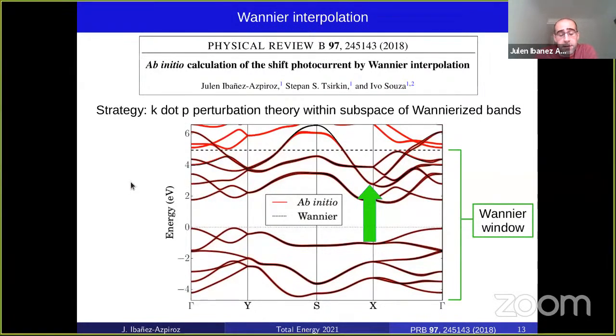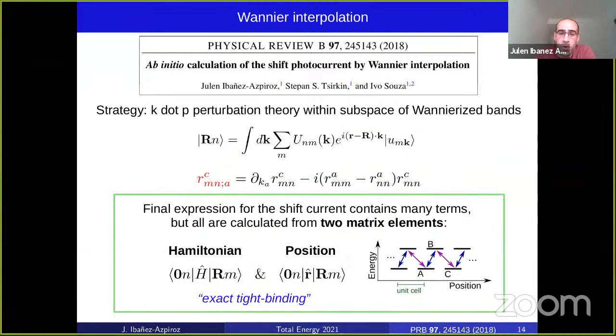Now, broadly speaking, in the Wannier formalism, one needs to consider a finite energy window where one wants to describe properties like the shift current spectrum. So then, if one follows the Wannier procedure, one can end up Wannier interpolating several quantities within this window. And this can be the band structure. This is a well-known example, but not only. One can also interpolate transition matrix elements, and that's our aim. That's where we have worked. We have tried to express the shift current transition matrix elements, and more specifically the generalized derivative, in terms of Wannier functions, in the Wannier function language.